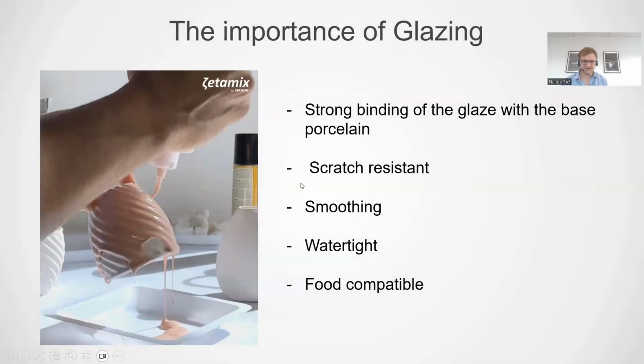Yes, so that's something I wanted to stress about this, which is that compared to any other coating process that you may have with different 3D printing material, this is very unique because glaze is more than just a coating. You actually have almost a fusion between the surface of your part and the glaze, which means you have an extremely strong binding between the two material, between the glaze and the part. It's usually almost impossible to scratch or chip out some of the glaze from the part. That usually never happens. If you try to do that, you're actually going to break the part. The glazes are scratch resistant. They're very smooth, which is really an interesting part.